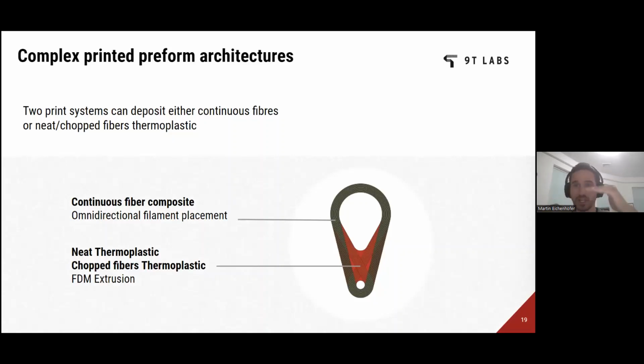And this can also vary throughout the thickness of the part, right? Because the fiber layup doesn't have to be the same for each layer. So it could also be a very complex stack of this hybrid printing approach. So what it really means is we can leverage the fibers, the fiber strength, and that's what we need to actually leverage the exceptional mechanical properties, which I talked about before.